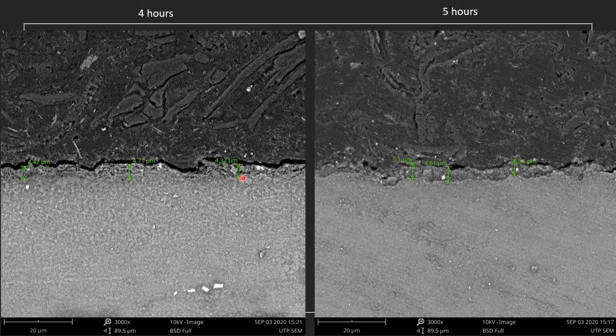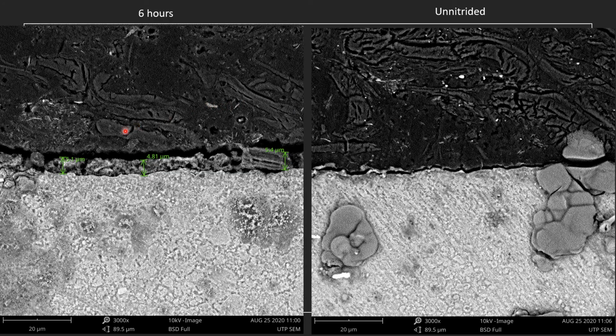4.7, and 4.3 micrometer. And here is the 5 hour nitriding time, where the nitride layer is recorded around 5.1, 4.6, and 5.1, which has a less significant difference compared to 4 hours and 3 hours of nitriding time. And here is the 6 hour nitriding time, where the values recorded are 5.1, 4.8, and 5.4, which also shows a less significant difference from 5 hour nitriding. And the right one here is the control sample, where we can see there is no layer formed between the phenolic powder and the material, the magnesium.